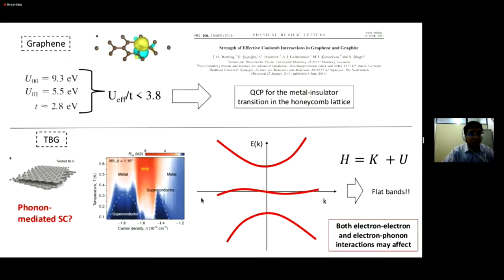in the twisted bilayer graphene, because in the twisted bilayer graphene, we have this very short flat band, almost this nearly flat band at the Fermi level. And in this case, since we have these flat bands, the cost of the kinetic energy is reduced, so the interactions are enhanced at some point. So even though we have this weak interaction in graphene, for this kind of systems they are important. This is why you have this Mott-like formation here, or the superconducting dome in the twisted bilayer graphene.